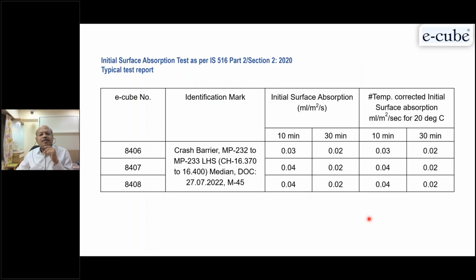So these are the typical results we generally get in our laboratory. You can measure at 10 minutes and also measure at 30 minutes. Then you can apply a correction factor to the values. So this is also one of the tests, a very good test, when you have to select the type of coatings on the surface. This is a very appropriate test for it.